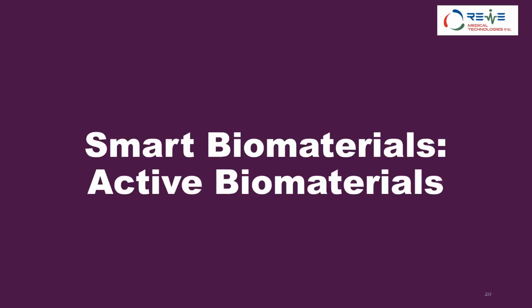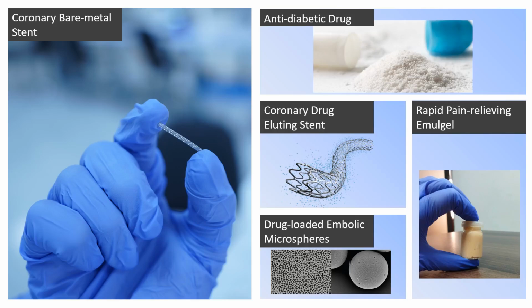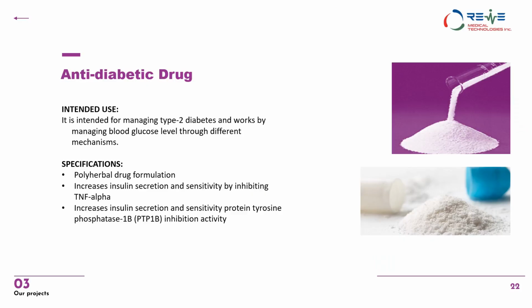In the next, active biomaterials, we have developed an anti-diabetic drug. We have also developed coronary drug-eluting stents and a rapid pain-relieving emulgel. We are right now developing drug-loaded embolic microspheres. The anti-diabetic drug that we developed is basically a polyherbal drug formulation, and it increases insulin secretion and sensitivity by different mechanisms of action. This drug was developed using active biomaterials, which hold and release the drug in 2 hours.